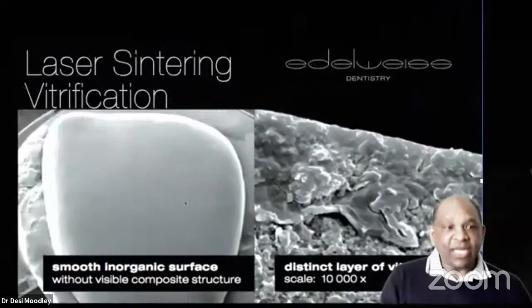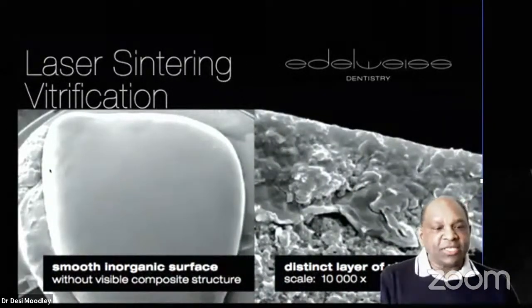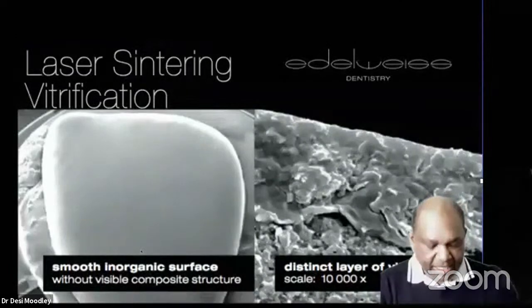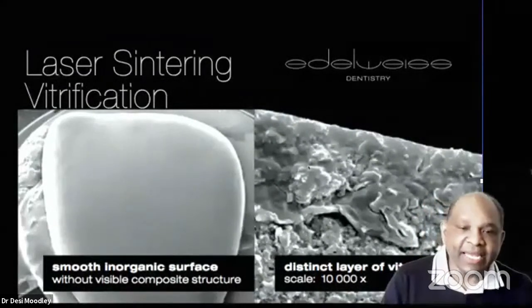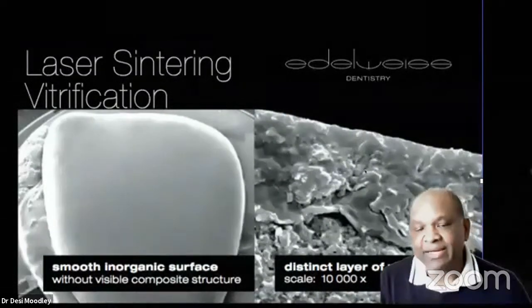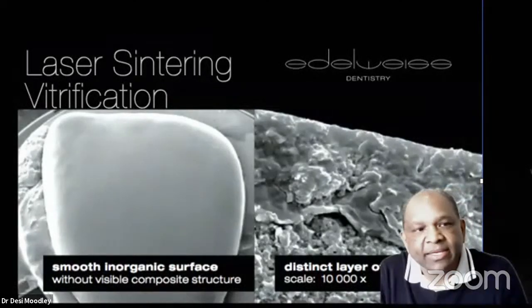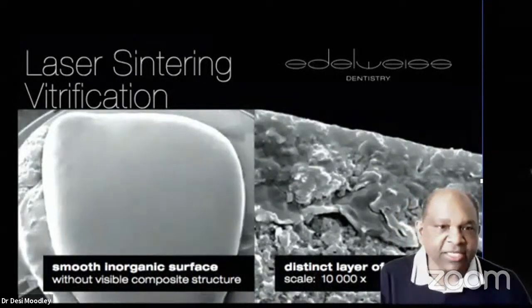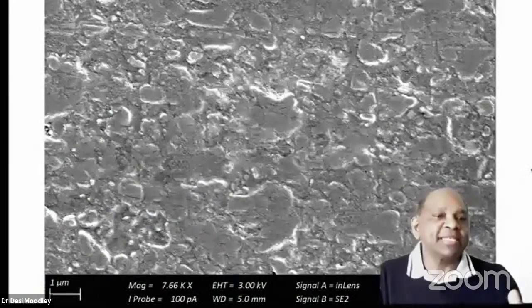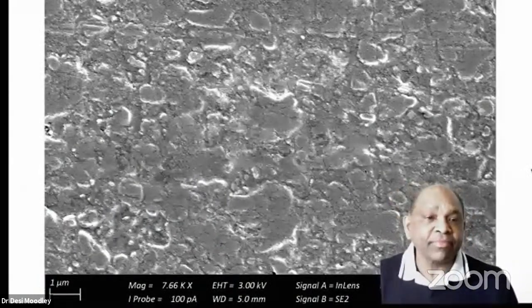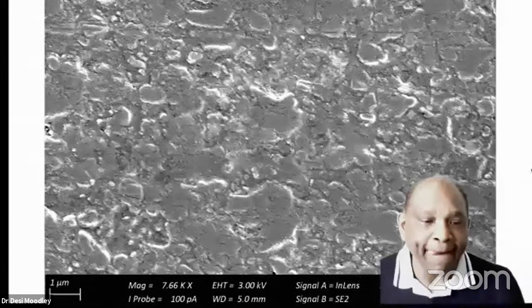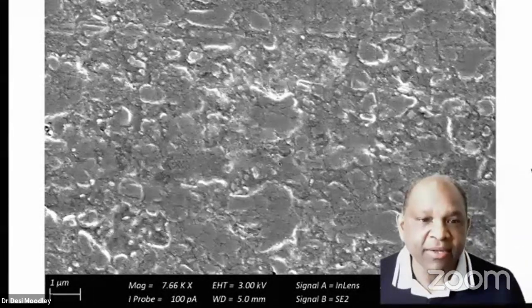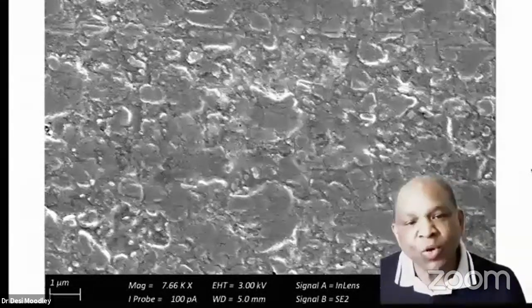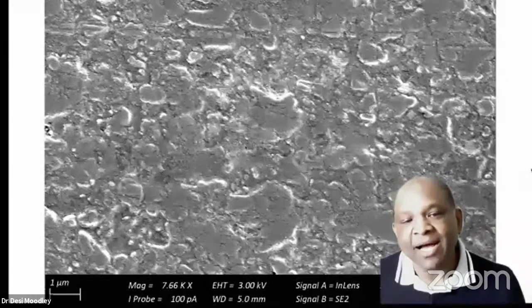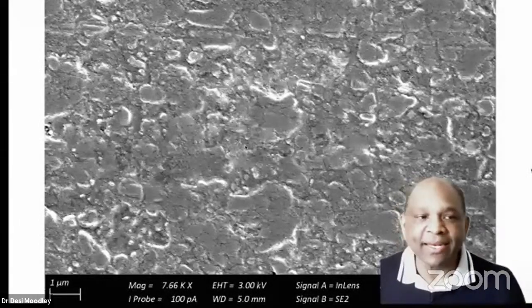So this is what it looks like. This is from Geneva University. It's a smooth inorganic surface, and there is a distinct vitrified layer that's present there. So they've shown that the laser sintering and vitrification process worked. This is a SEM that we did, or I did, at 7,000 magnification, showing that the glass particles are fused together with very little resin present.